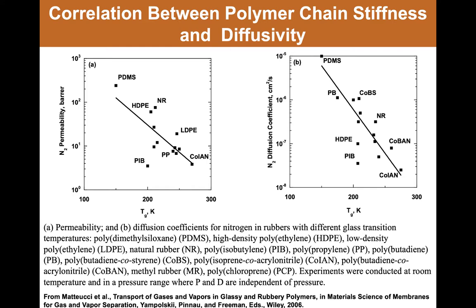This is showing a graph of a correlation between transport properties, both permeability and diffusion coefficients, and the glass transition temperature for a number of rubbery polymers, and is making the point that the more rigid or stiff the polymer chain is, the lower is the diffusion coefficient, and therefore lower is permeability. Now, these data could also likely be highly correlated with free volume, because free volume will typically go hand in hand with chain stiffness. As you go to higher glass transition temperature materials, the free volume would change accordingly to change the transport properties.